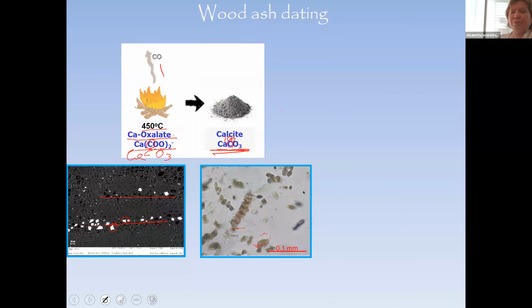that ash should be a perfect material for dating, in this process of emission of carbon monoxide, this process is not in equilibrium with the atmosphere, so carbon monoxide can be introduced and exchanged, and this carbon monoxide is not like the carbon dioxide with the C14 used for photosynthesis, it is not in equilibrium for as much as the C14 is involved. So in this case, ash is a very complicated material to date.